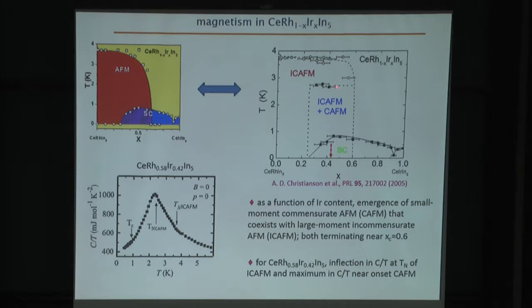If we cool it down just a little bit further, roughly a degree or so, a small moment commensurate antiferromagnetism appears, and it coexists with this large moment incommensurate antiferromagnetism. And finally, if we cool it down below a degree or so, we have superconductivity. So very, very complicated. Nevertheless, these phase boundaries at this composition are reflected in specific heat, which is shown here. So what we see is that there is an inflection point in specific heat divided by temperature at the onset of this magnetism. The peak in specific heat divided by temperature corresponds essentially to the development of this phase boundary here. And finally, there is a very small anomaly that's associated with the appearance of superconductivity.